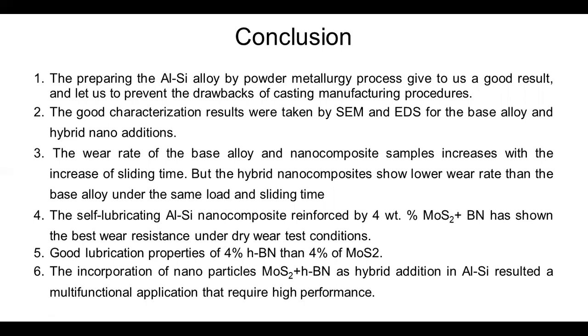Third, the wear rate of the base alloy and nanocomposite samples increases with the increase of sliding time. But the hybrid nanocomposites show lower wear rate than the base alloy under the same load and sliding time. Fourth, the self-lubrication of aluminum silicon nanocomposite reinforced by 4% molybdenum disulfide plus boron nitride has shown the best wear resistance under dry wear test condition. Fifth, the good lubrication properties of 4% hexagonal boron nitride than 4% of molybdenum disulfide. The incorporation of nanoparticles, molybdenum disulfide plus hexagonal boron nitride as hybrid addition in aluminum silicon results in multifunctional application that require high performance.